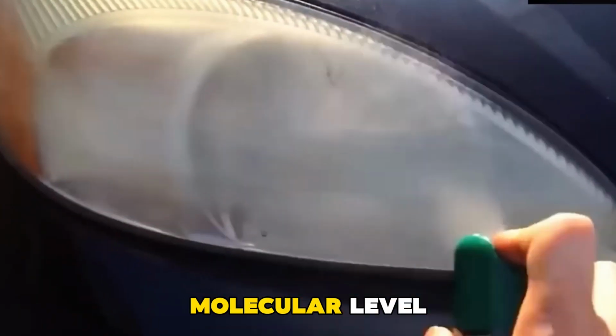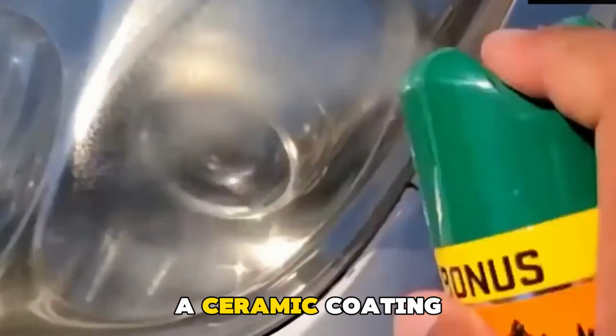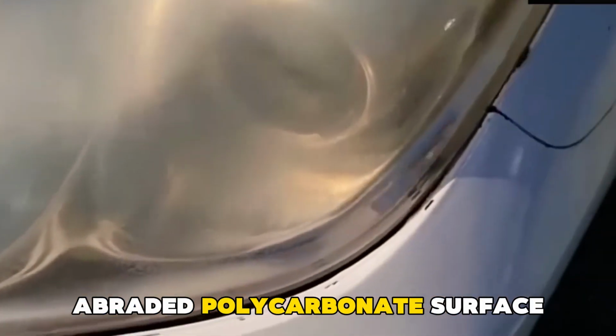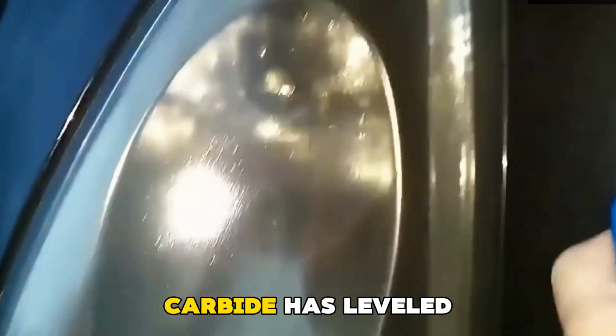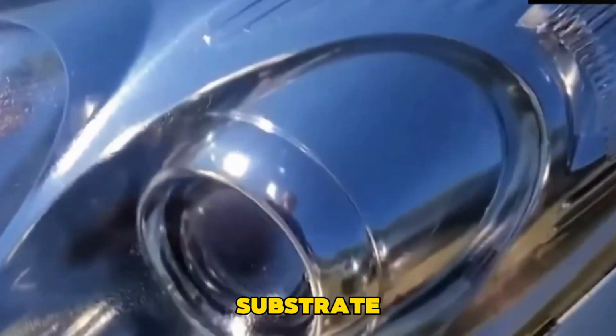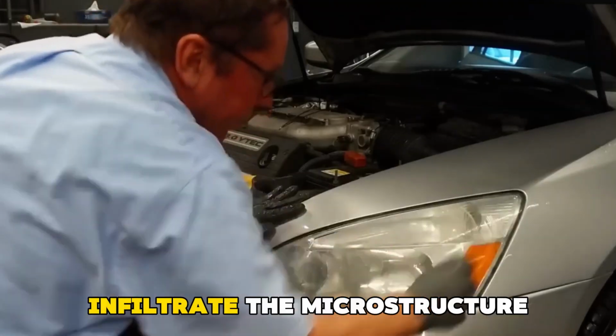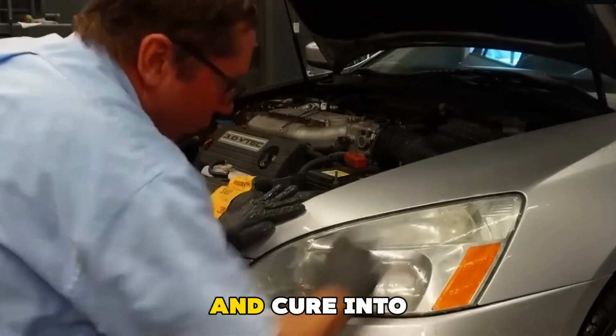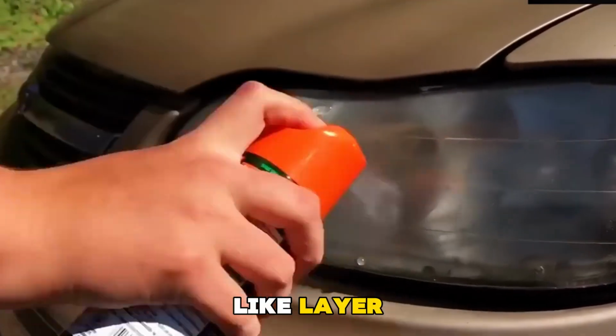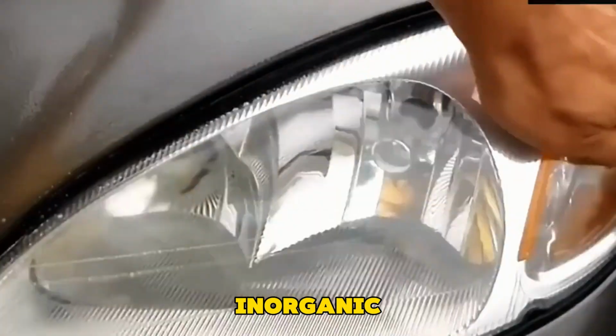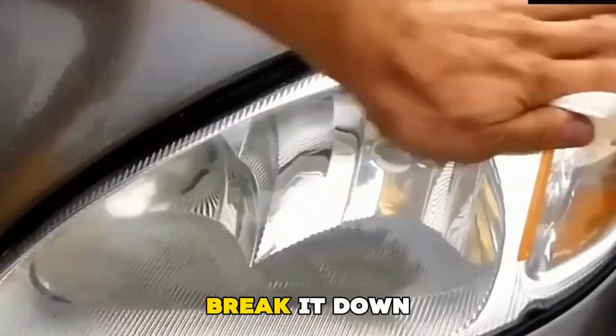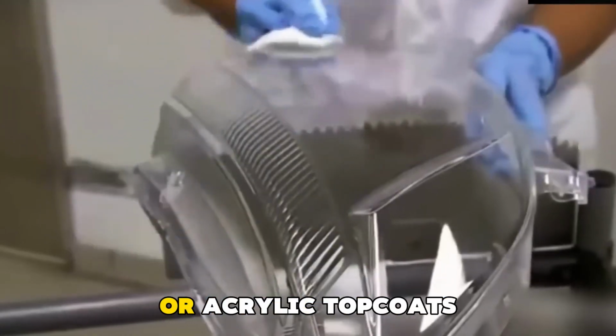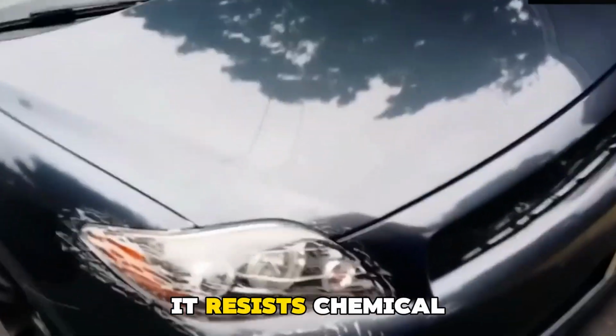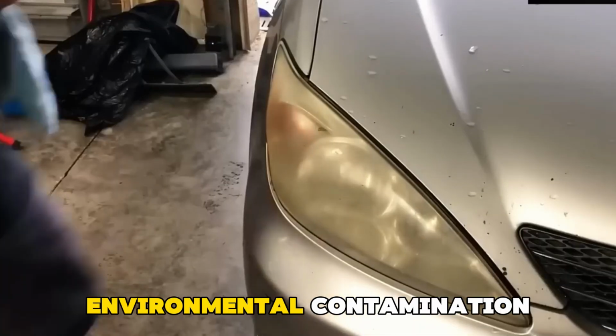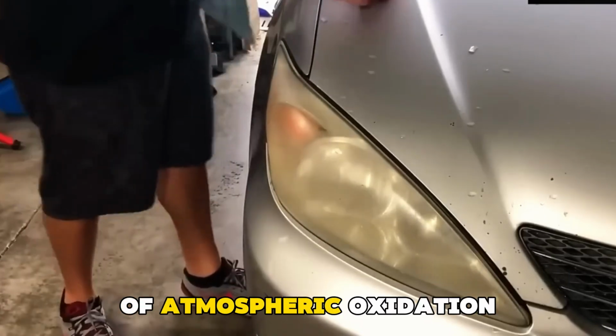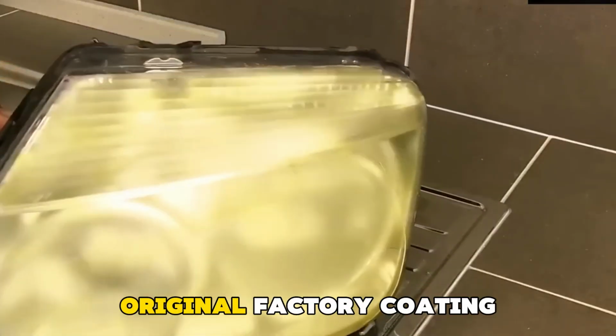Chemically, at a molecular level, when you apply a ceramic coating to a freshly abraded polycarbonate surface, one that silicon carbide has leveled and cleaned to a near-perfect substrate, the SiO2 molecules infiltrate the microtexture of the surface and cure into a continuous glass-like layer. This layer is inorganic. UV radiation cannot break it down the way it breaks down plastic or acrylic topcoats. It resists chemical degradation, environmental contamination, and the kind of atmospheric oxidation that destroyed the original factory coating.